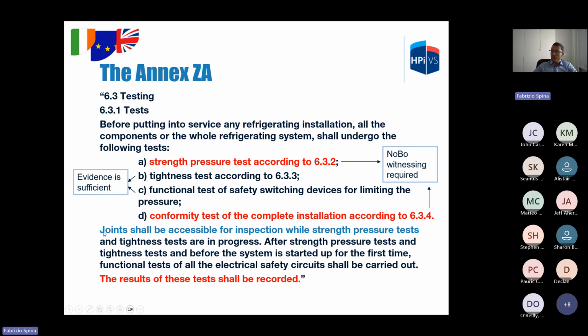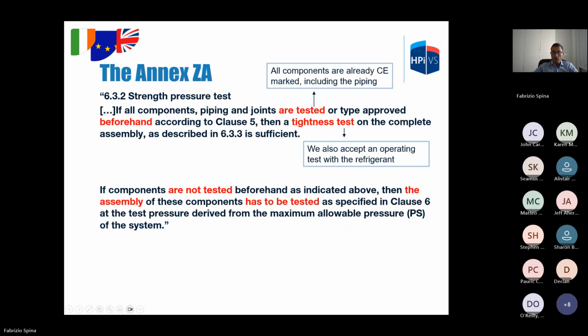Joints, especially welding joints, shall be accessible for inspection while strength pressure tests are in progress. That's to allow the inspector to verify if there is leakage or not. The result of this test shall be recorded. So for the strength pressure test, we have basically two cases.